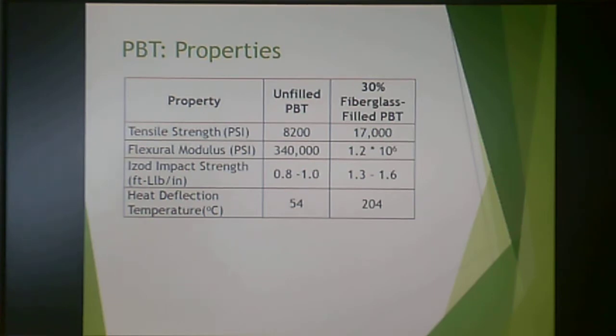You can kind of see the effect of fillers here. So here is an unfilled PBT and here is a 30% fiberglass filled PBT. You more than double the tensile strength, you more than double the flexural modulus. You get better impact strength and you get much higher heat deflection temperature. So this is an example of what fillers do for polymer properties.